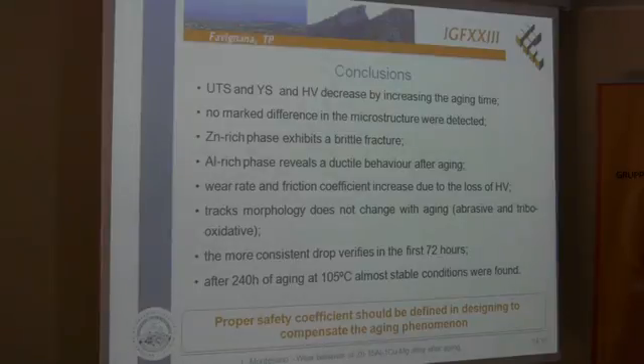We also observe that the first and most consistent drop of the mechanical properties is, of course, in the first 72 hours. And then the material reaches a sort of stable condition that is confirmed also by the test performed at 240 hours. So, as an indication in the designing of parts with this alloy, it can be really useful to define a proper safety coefficient in order to compensate for the effect that the aging has on the